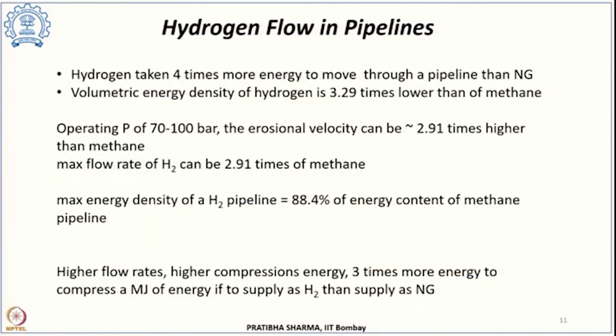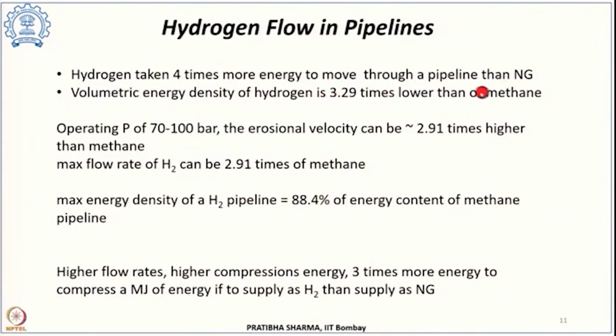Now, when we consider hydrogen flow in pipelines, we know that it takes more energy to flow hydrogen as compared to natural gas through a pipeline, roughly around 4 times more energy. We also know that the volumetric energy density for hydrogen is 3.29 times lower than that of methane. If we consider that the operating pressure of hydrogen in the pipeline is between 70 to 100 bars, and the erosional velocity allowed is approximately 2.91 times more than that of methane, then the maximum flow rate for hydrogen could be 2.91 times that of methane. This gives the maximum energy density of hydrogen in a given pipeline at a certain temperature and pressure as 88.4% of the energy content of methane. So, this is simply 2.91 divided by 3.29.